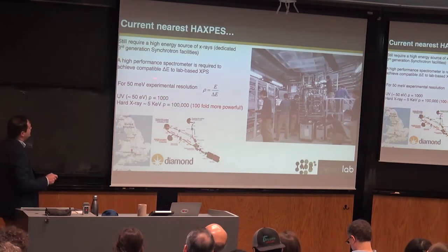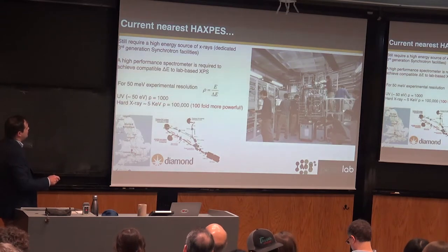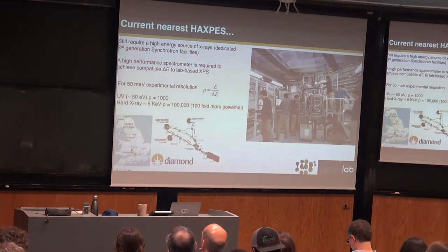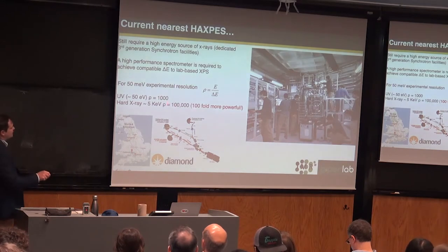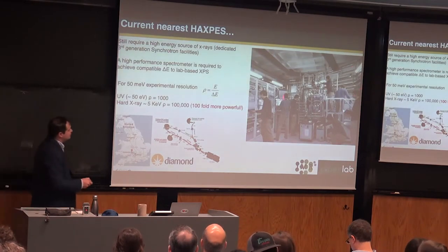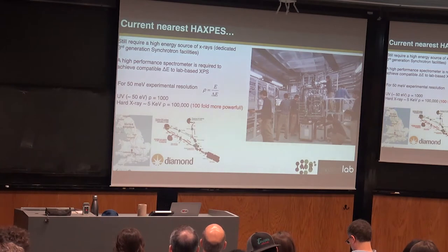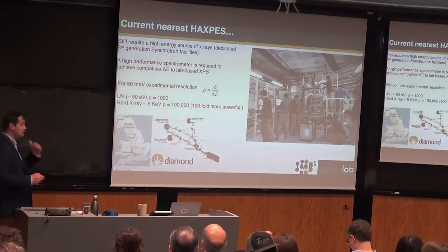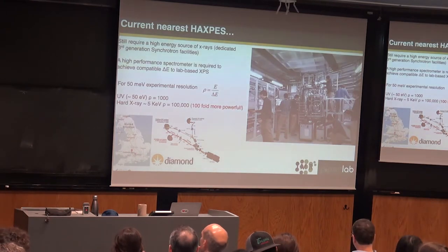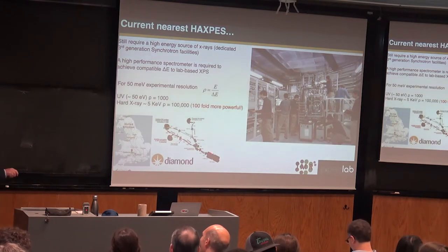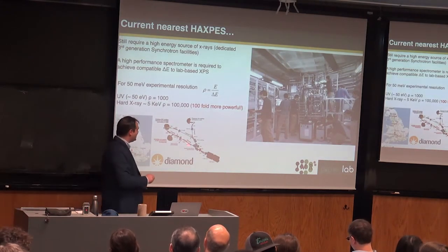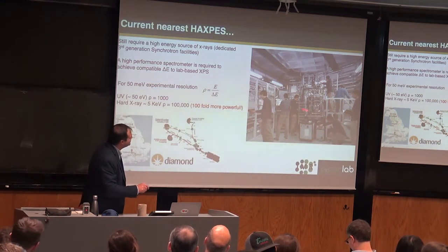And so if you have a more traditional UPS system with a resolving power of the order of thousands, to do the equivalent absolute energy resolution, you would have to have 100 times more powerful spectrometers. So it's only with the advent of the early 2000s that we started having spectrometers that could be bolted onto synchrotrons to do equivalent core level and valence band spectroscopy with HAXPES that you could do in a lab-based system with XPS. And so that meant I had to explain to my parents why I live in America, but often go to a place an hour's drive from their house to do the measurement, which I say is critical for my career. And this is one of the students doing all the experiments.